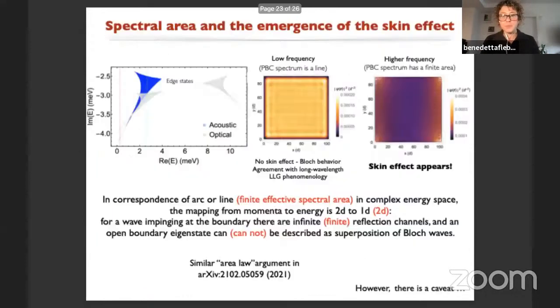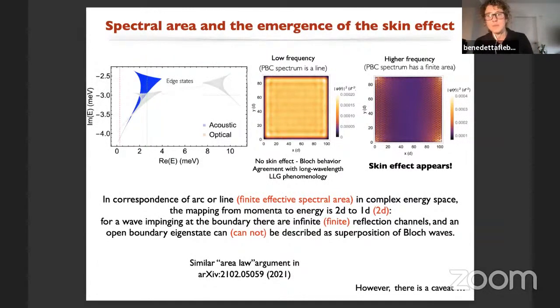So what's going on? We try to understand, at least in part, what we see. So first of all, let's try to understand the temperature dependence. As you can see here, this is a plot in which I'm showing you in blue the acoustic, and here in orange the optical periodic boundary condition spectrum. So the one that you would obtain just by setting periodic boundary conditions. The gray ones are instead the open boundary condition spectrum. You are of course observing a discrepancy between the open and periodic boundary condition spectrum, but this is also another expression of the emergence of the skin effect and the breakdown of the bulk-edge correspondence.